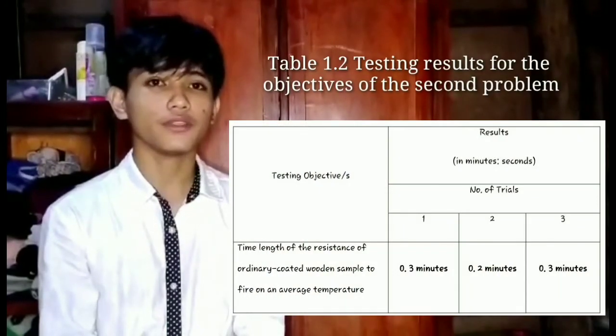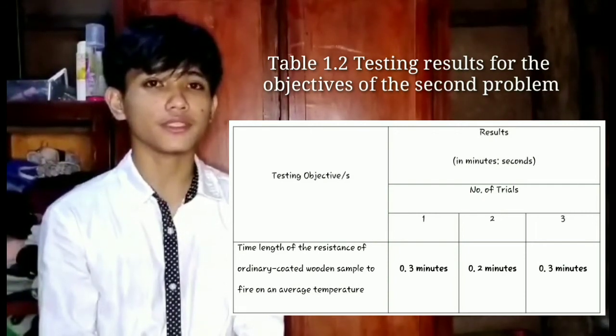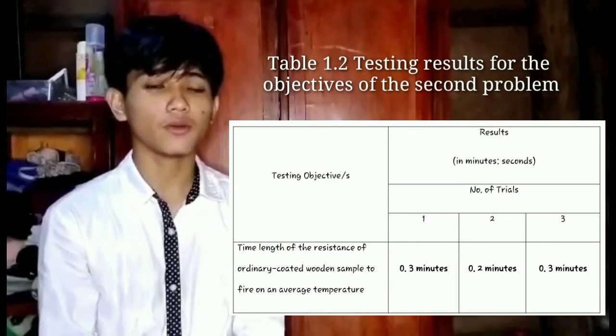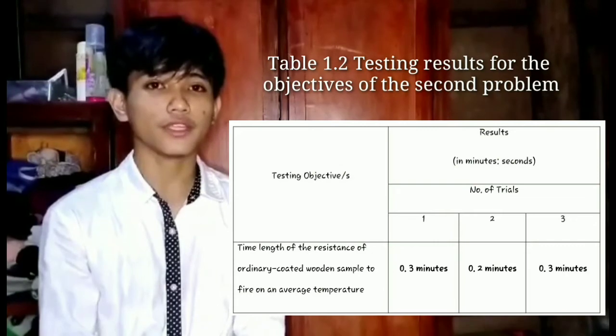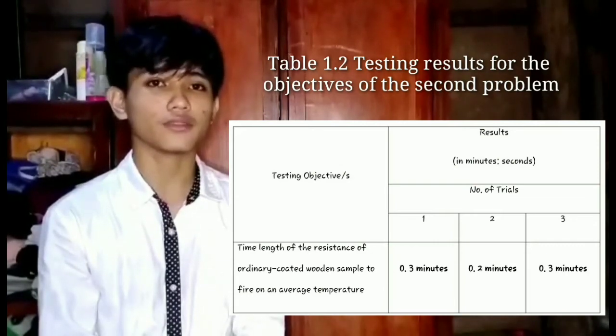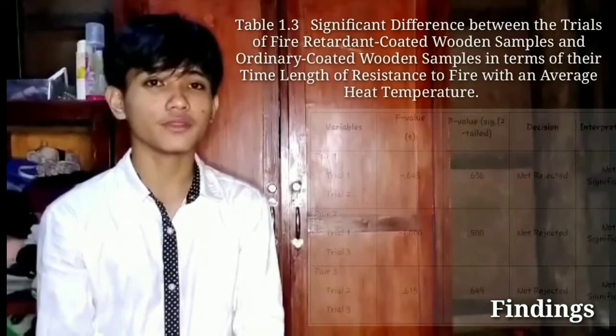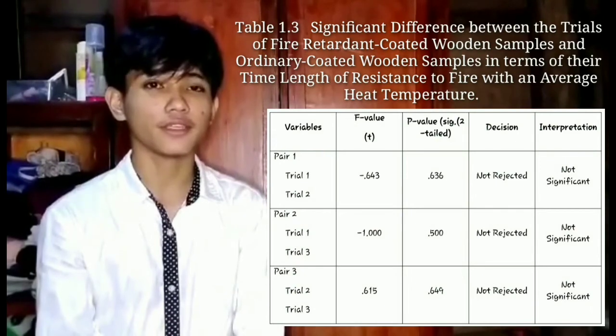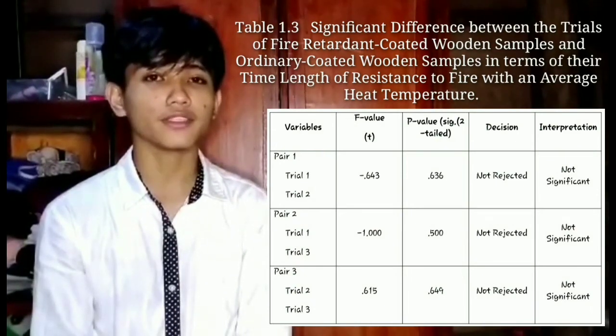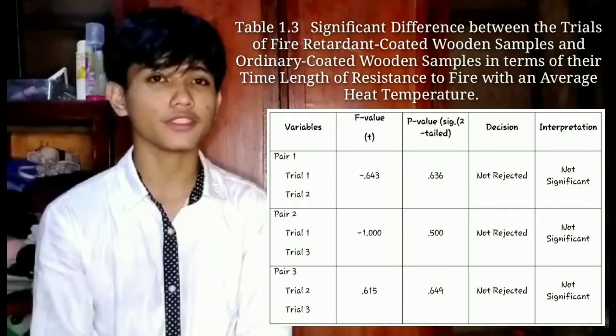Moving on, in the second testing of sample, which is wood coated with ordinary paint, the first trial resulted in 0.3 minutes. On the second trial, 0.2 minutes, and on the third, 0.3 minutes. So with this gathered data, we can now determine if there is a significant difference between the 2 samples in their time length in resisting fire. Using a statistical tool, we now have the results. Based on the result, there is no significant difference between the 2 samples in their time length in resisting fire. This is because the p-value of the sample is greater than the significance level alpha, which is 0.05.